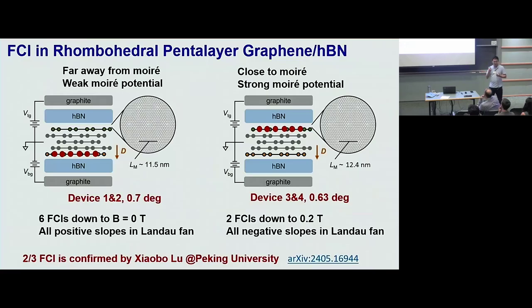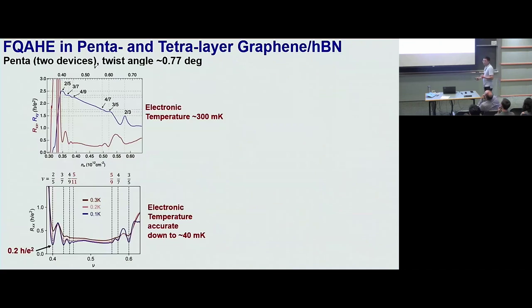They use a 6-layer rhombohedral graphene instead of 5-layer. They observe 2/3 FCI there. So the physics here is repeatable. And in our lab, we keep studying this fractional quantum anomalous Hall effect and FCI using DC transport.